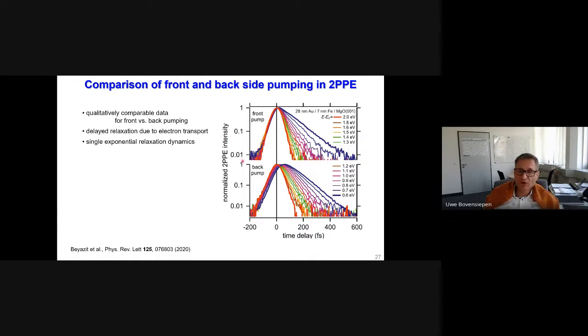Okay, let's look to the data. And I show you on top here 2-photon photo emission intensity for front side pumping as a function of pump probe time delay. The different colors, these are the energies above the Fermi level. And here in the lower part, you see the backside pumping. Where the 2 data sets agree very well is this slopes in the relaxation. This is a logarithmic scale, so this linear behavior is simply measuring the hot electron lifetimes, and at lower energy, following the Fermi liquid theory, for example, we have a slower relaxation compared to higher energy. So this we understand very well.